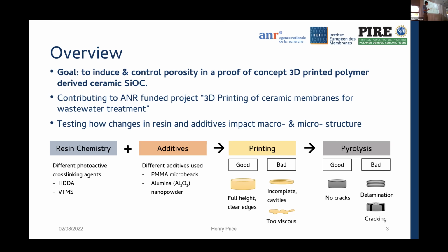And now after pyrolysis, one of the main issues I was working on is cracking of the part, because as you know, during pyrolysis, there's gas release from the sample, and it needs a place to go. So oftentimes the samples will crack. The two main types of mechanical failure after pyrolysis were what I call delamination, which is layered cracking between print layers, and more randomized cracking, which is along the vertical axis.